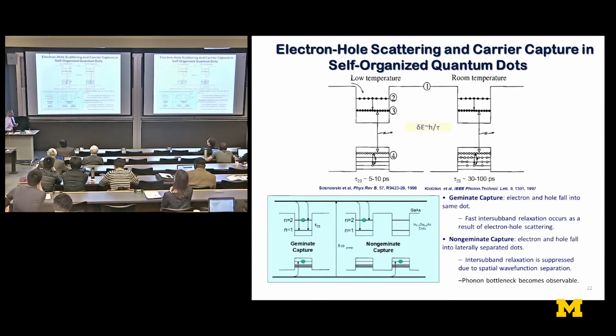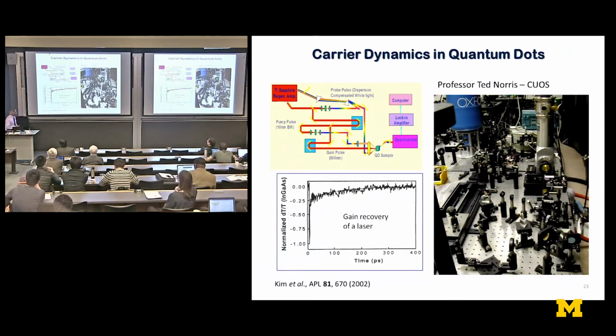So we started understanding all our results. The other monumental result that came out of his lab was this direct measurement of the gain recovery of a quantum dot laser. And of course, we saw that by this electron hole scattering, the gain recovery is very, very fast. And you will see that this result, which was again repeated in Japan, by this time we had found out that I had two other competitors around the world. One was Yasuhiko Arakawa, and the other one was Dieter Bimberg's group in Berlin. And so this result, you'll see the relevance of this result later on.